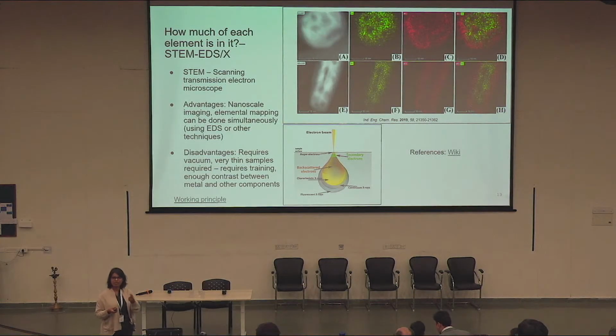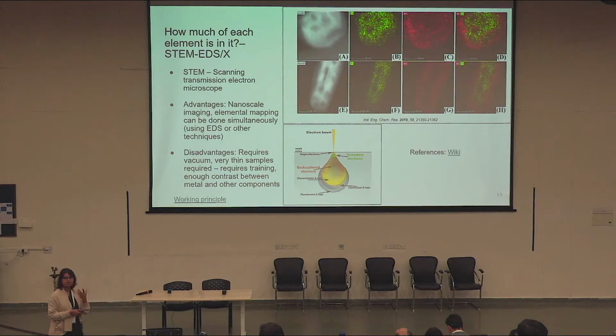Basically, I'm clubbing the EDXRF with the transmission electron microscopy measure. And then what is the result is that these are two images. This is a mixture of iron and manganese that is present as a spherical particle and also a rod, and images that you would get when you're basically measuring the electrons that are ejected from your sample or transmitted through your sample.